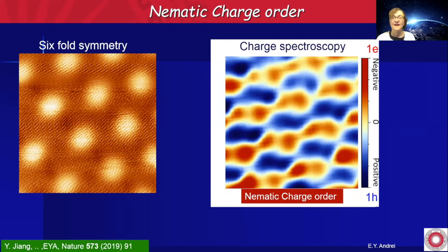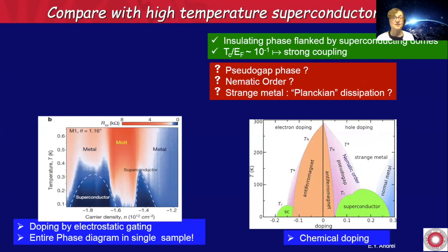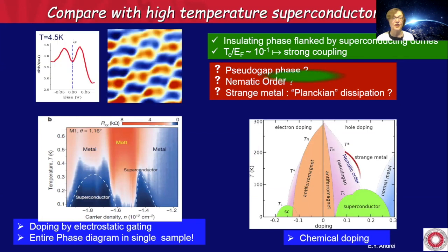So the red lines correspond to 1 electron per Moiré cell. Blue is 1 hole per Moiré cell. And you see how beautiful these alternate. So you really have some charge order that is established there. And this charge order is only when the Fermi energy is within the flat band. As soon as you go outside of the flat band, or as soon as you apply a magnetic field that's above about 8 Tesla, this goes away. So this convinced us that this is an intrinsic rearrangement of the charges of the electrons due to the correlations in this system. So now we can reassess where we are. So yes, we have a pseudo gap phase, just like in high temperature superconductors. We have nematic order as well.